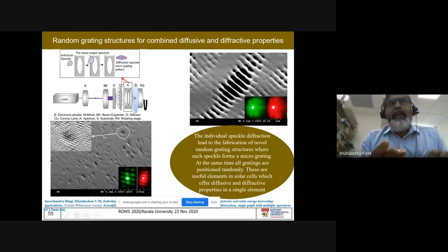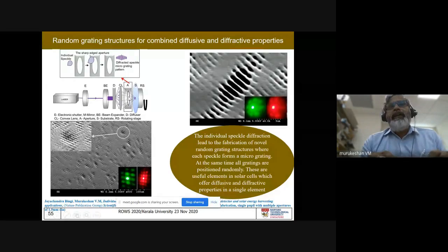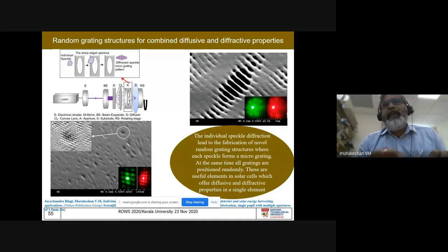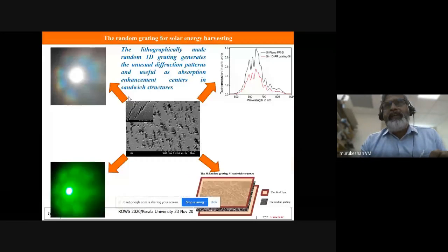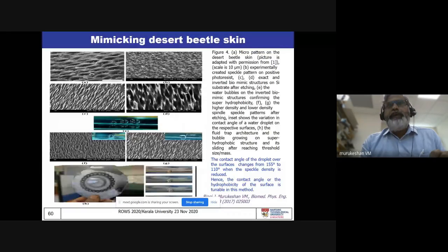There is another element here. And you can see that these diffraction patterns go through an aperture in such a way that the zeroth order is going to be effective in the far field. So what is going to happen is that in the far field, when you are doing the patterning, the speckles are going to get elongated in this kind of a shape. It's very, very random, and this structure exactly mimics this Namib beetle structure. This is taken from a literature that is published in Nature, and it was mimicking exactly the same structure.